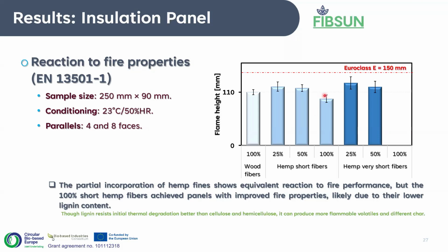But the main point to look at is that there's already a class of performance, and in this case we see that all the products pretty much achieve lower flame height for this class, but more importantly, we see that with the short fibers, the slightly longer fines, there is even better performance. And the main point here is that this is the particular fiber with the lowest lignin content. And of course, lignin can also play a very important role, especially when it comes to the reaction to fire properties of lignocellulosic material.